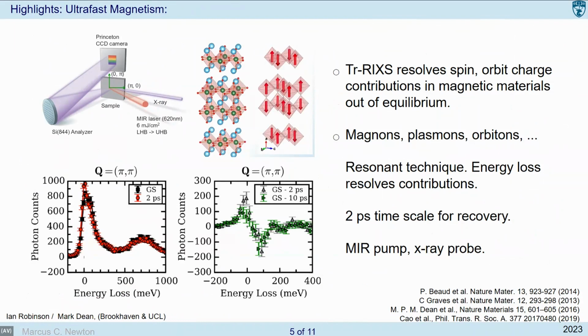The energy loss is shown here from the measurement, and you can see that they're able to resolve the time-varying energy loss as a function of the pump-probe delay. You can see after 2 picoseconds, they can see some variation in the energy loss, and also here. And this is a resonant technique, of course.